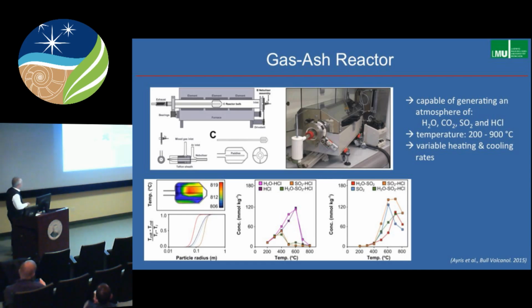And you can measure essentially the pickup of the gas components which are later leached out of the materials, and you can see that at very, very high temperatures, at 600 degrees Celsius, you have a take-up or a pickup of a significant amount, for example, of chlorine from HCl, which is used as a gas input, or from SO2, which is used as a source of sulfur in these experiments.